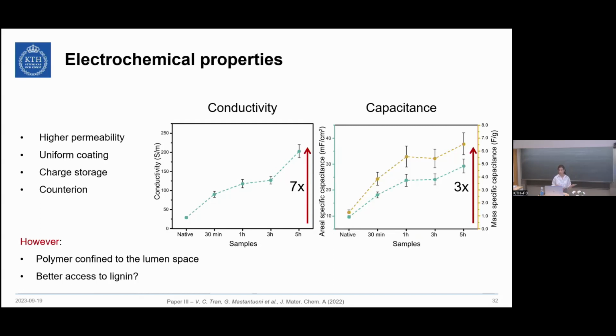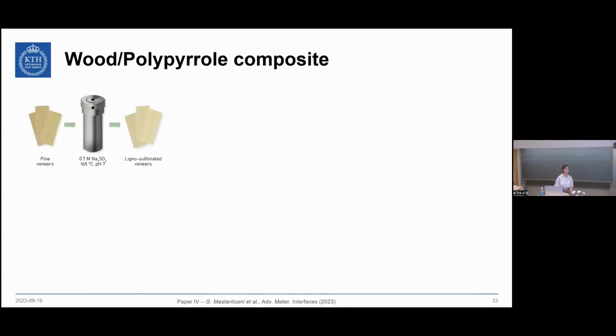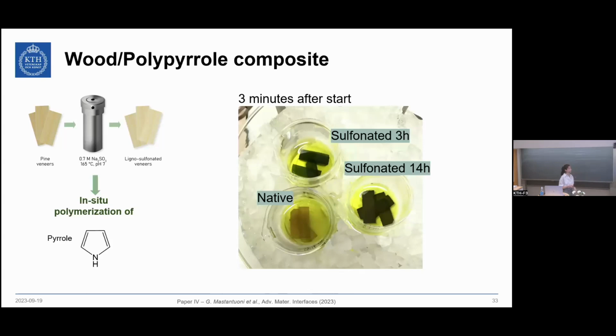And one possibility to do this is to use smaller molecules. So in this case, we follow sulfonation with in-situ polymerization of pyrrole. So we're using monomers instead of pre-polymerized polymer. And here again, the sulfonation seemed to improve the polymerization already after only 3 minutes after the start. And we focus on 2 different sulfonation times, and we can see here again the polymer is black. The sample turned black for the sulfonated one, but they stayed native color in the case of the native wood.